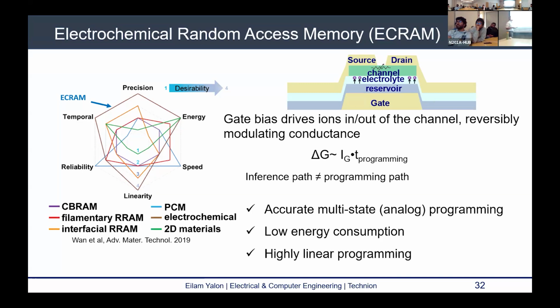And ideally, these ions are intercalated into the channel, so they modulate the conductance. So if we can tune the concentration of ions going into the channel and out of the channel, and if these ions are dopants, they change the conductance because they change the carrier concentration. Then the change in the conductance is proportional to the ionic gate current, which we can tune with applied voltage or even current, multiplied by the programming time.